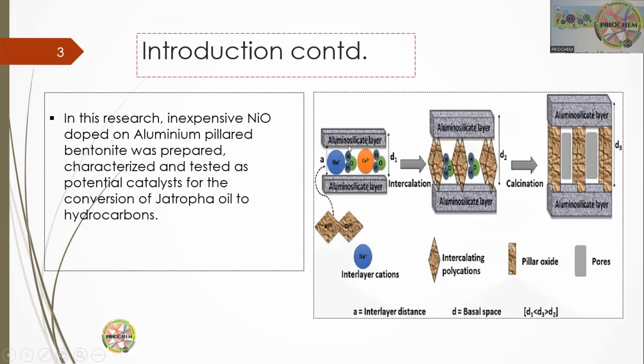You have the aluminosilicate layer. In between them, we have the interlayer cations. When you introduce, in our case, aluminium, to replace the interlayer cations, that is the intercalation, and after you calcine, you get a pillar. By doing that, you can increase the thermal stability, the porosity, and the surface area, because the d-spacing will increase, and that will translate into an increase in surface area.